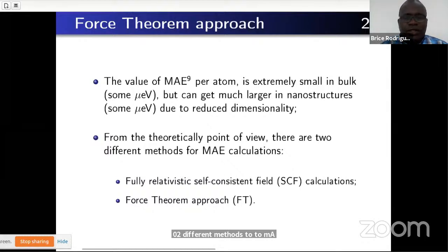The first one is the fully relativistic self-consistent field calculation, and the second one is the force theorem approach. Accessing the MAE for systems containing hundreds of atoms by the former approach is especially challenging, since it requires a well-converged charge density as well as a time-consuming computation.